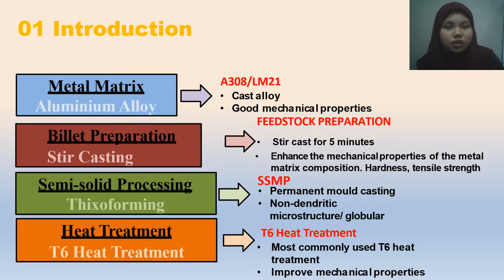It is a cast alloy that has good mechanical properties, and for the billet preparation, I have been using a stir casting process to make the feedstock. The duration was 5 minutes of stirring, to enhance the mechanical properties of the metal matrix composite. The next process was thixoforming for the SSMP, with the purpose of reaching the non-dendritic microstructure. The last process was T6 heat treatment, to improve the mechanical properties of the material.